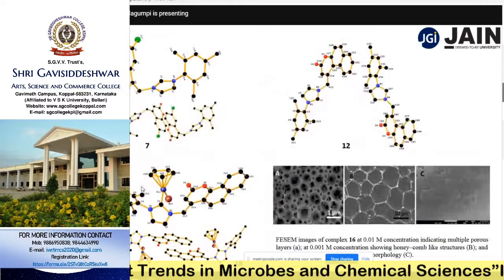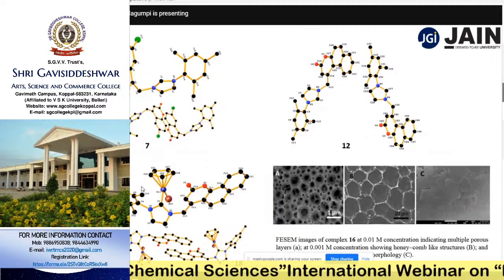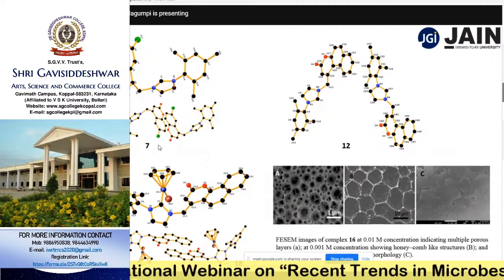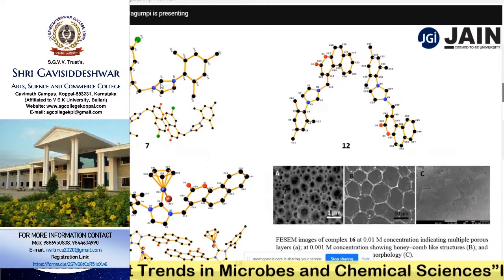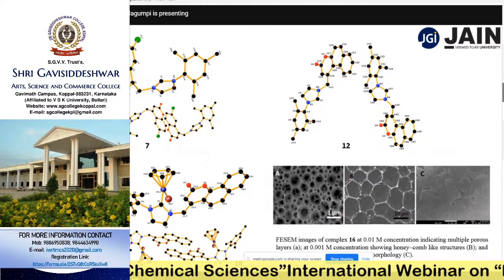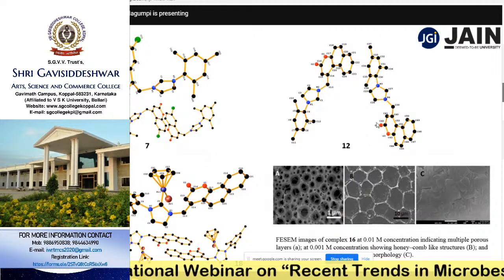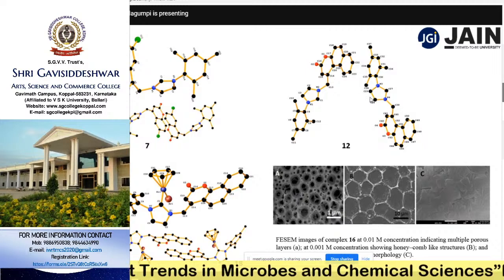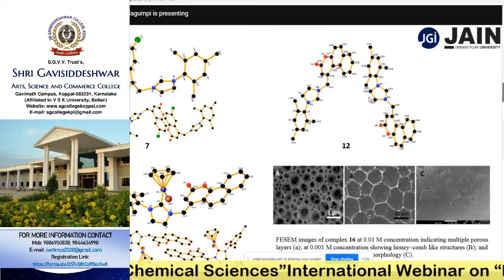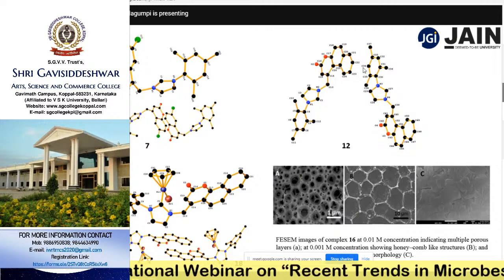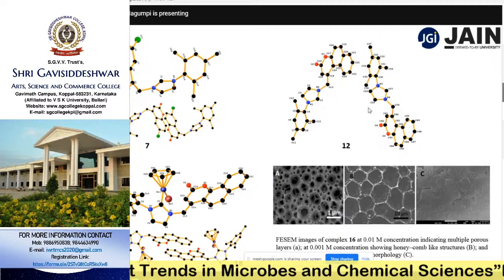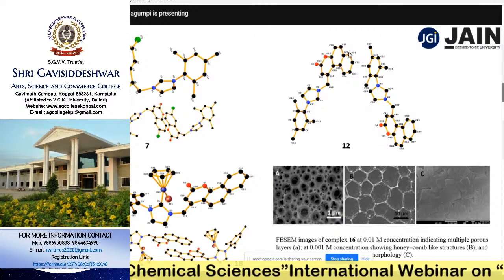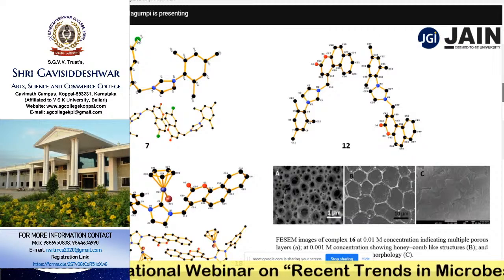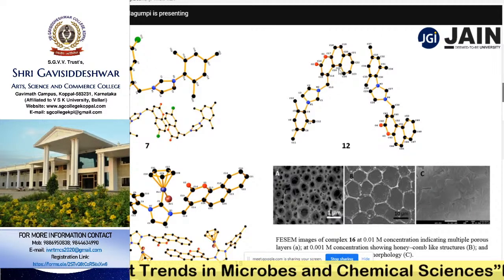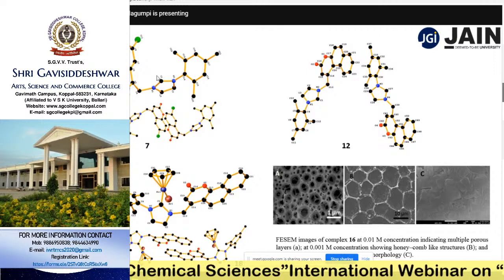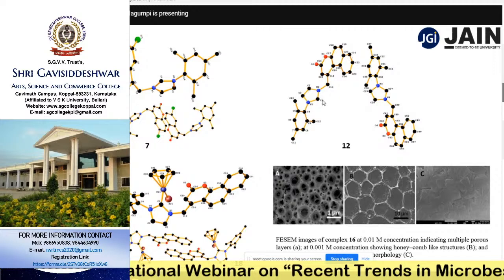Further, representative salts and a nickel complex have been evaluated for their structure by single crystal X-ray diffraction. A salt is present here, having mesityl substitution, imidazolium, with a chloro-substituted coumarin derivative, and pi stacking interactions. Similarly, salt 12 is crystallized in two crystallographically different but chemically same entities. Chemically they are the same, but crystallographically there are small differences. This is the crystal structure of salt 12, which has mesityl-substituted imidazole and 7-8 benzannulated coumarin. So this gives the steric variation around the metal center, while the other is believed to provide the electronic variation around the metal center.